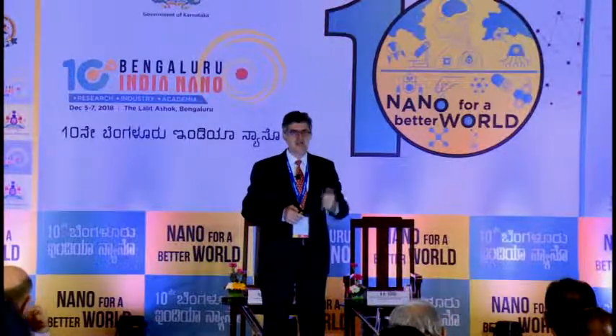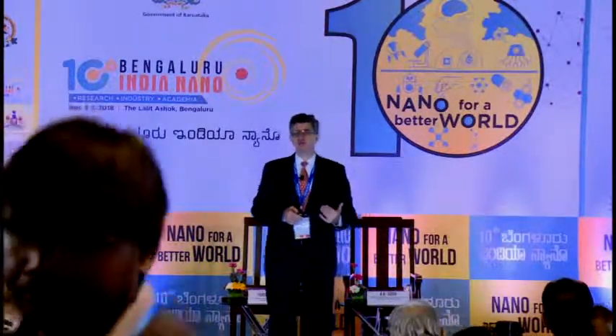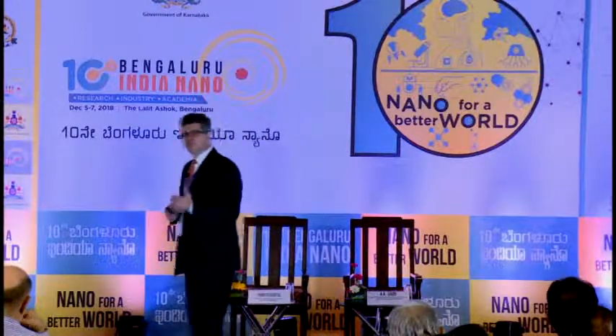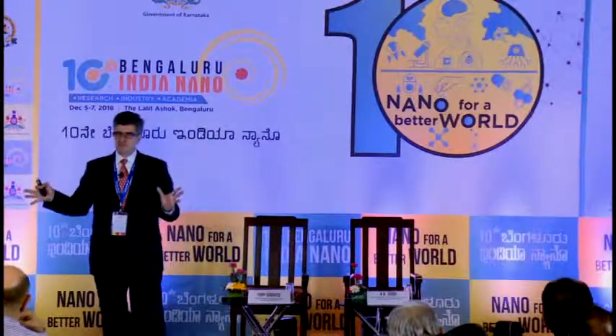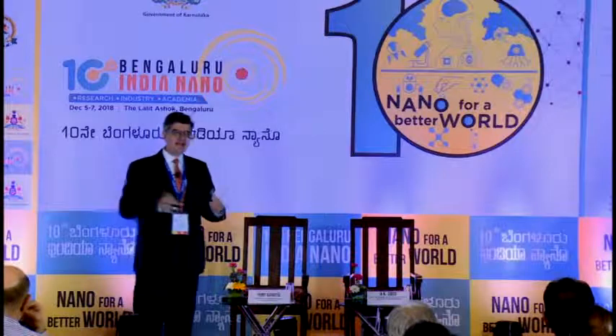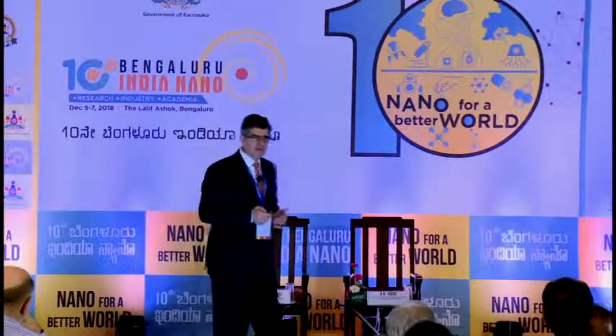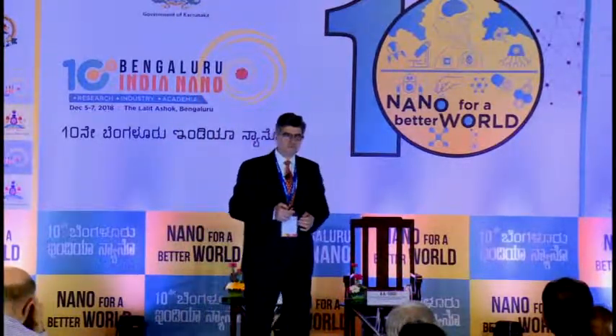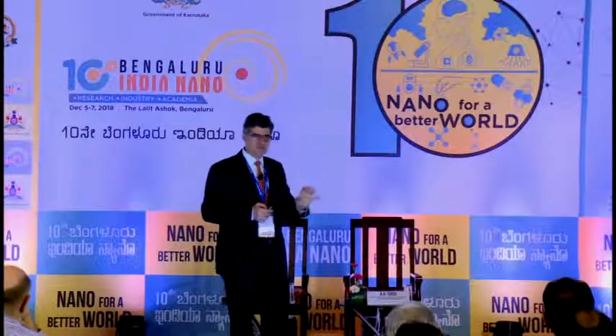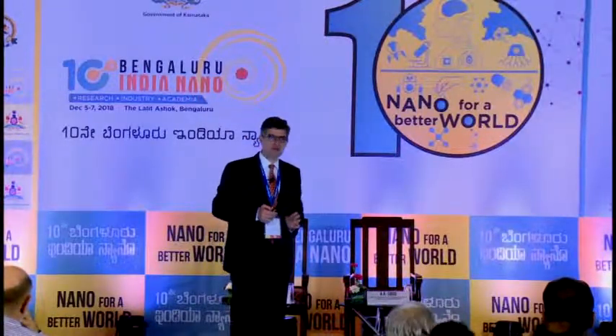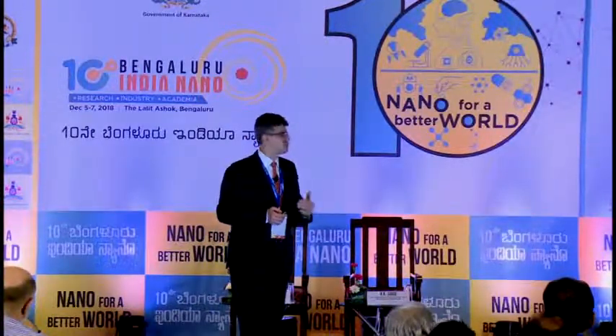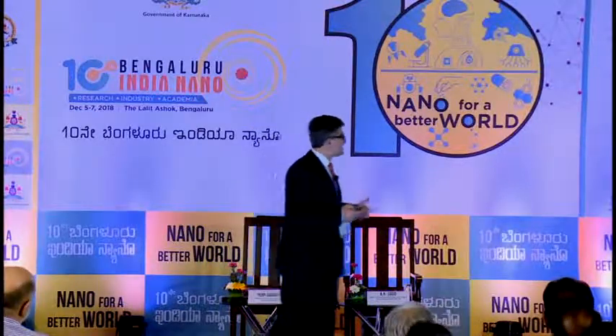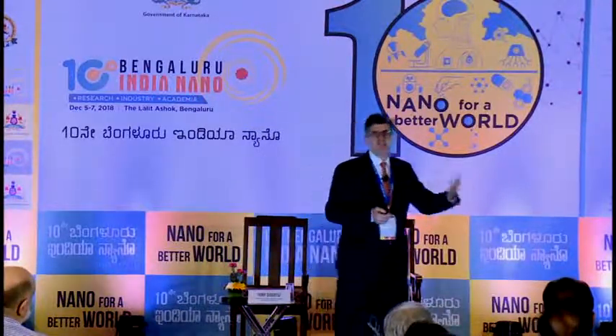And also, just about a month ago, a paper appeared online, which should be in the next issue of ACS Nano, showing that it's possible to adsorb urea molecules for building an artificial kidney because of the large surface area and, again, the high negative charge on MXenes. Urea, a small molecule that is very difficult to absorb, can be absorbed in very large quantities here. So, basically, as we move step by step, applications are emerging.